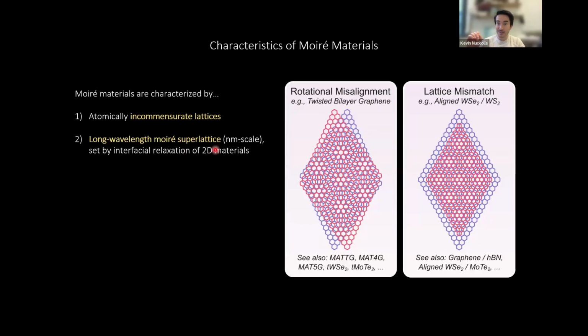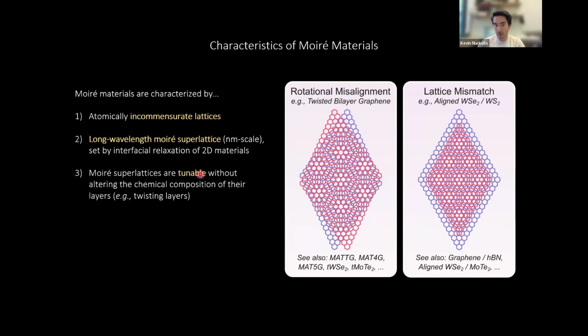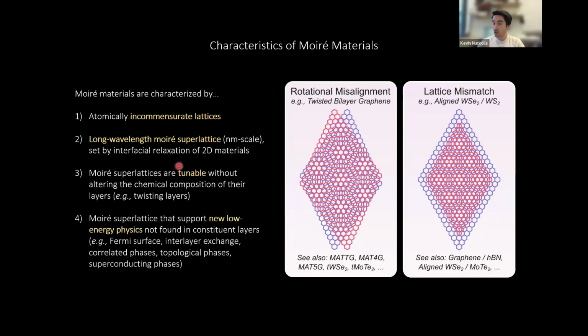Really importantly, Moiré materials have Moiré superlattices that are tunable without having to affect any of the chemical composition of their layers, oftentimes tuned by the twist angle that you set between the two crystals. And finally, with this tunable structure comes tunable low-energy physics that is often not found in the constituent layers. So a lot of experiments have been really focused on how this affects the Fermi surface or the band structure of Moiré materials, how this can affect interlayer coupling, or how this can give rise to a wide variety of quantum phases of matter.